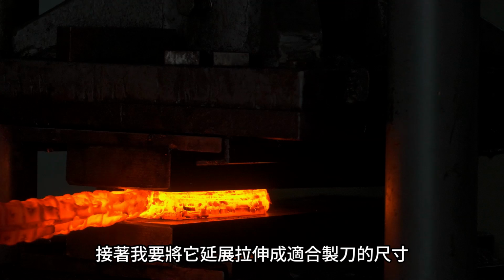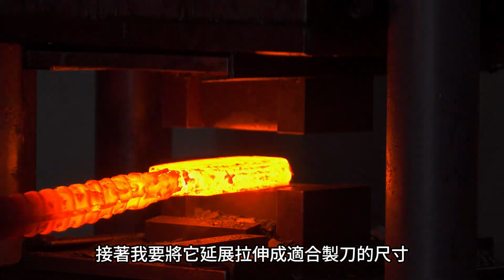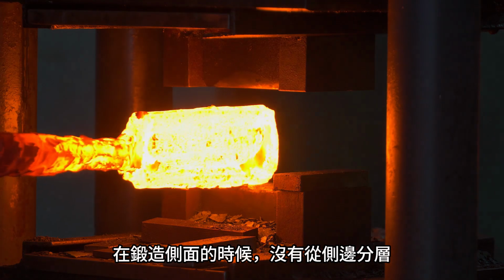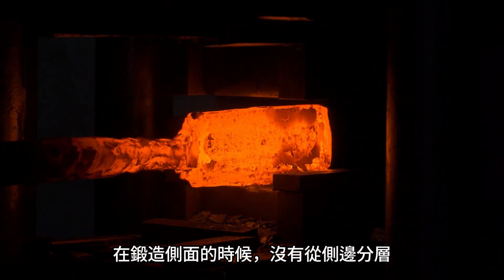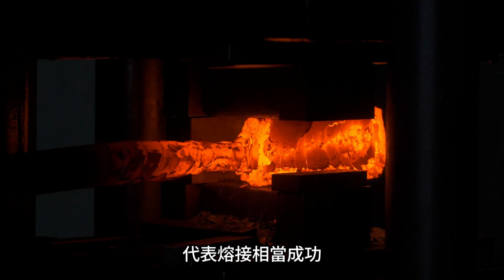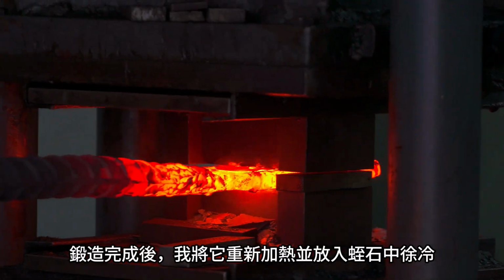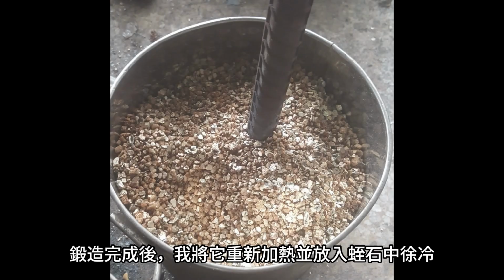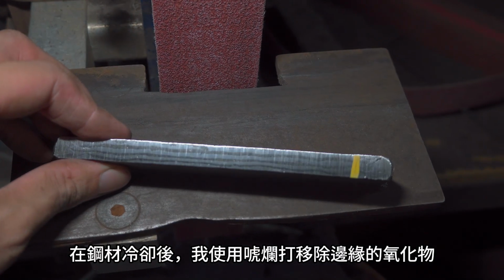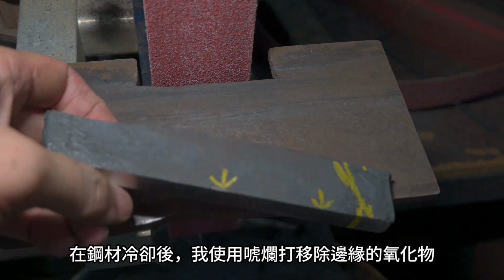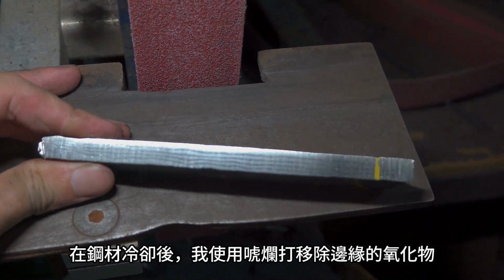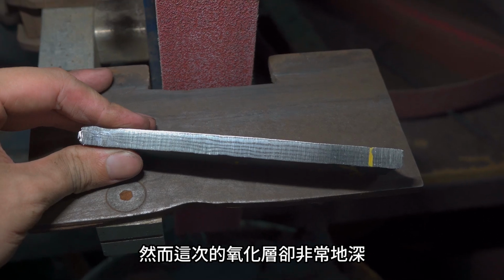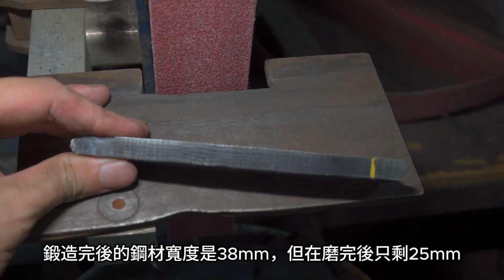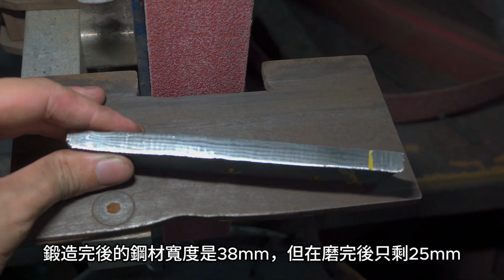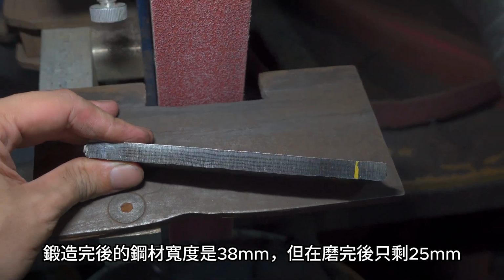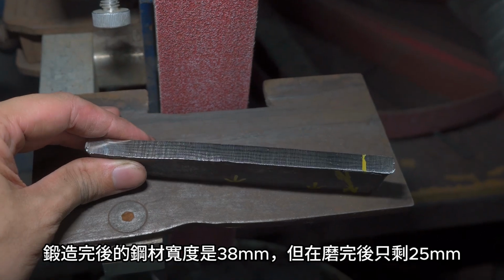Next, I need to flatten and stretch it to a size suitable for making a knife. During the side forging, there was no delamination, which means the welding was very successful. After forging, I reheat it and press it in vermiculite to cool slowly. After the steel cooled, I used an angle grinder to remove the oxide layers from the edges. However, this time the oxide layer was very deep. The width of the steel after forging was 1.5 inches, but after grinding, it was reduced to just 1 inch.